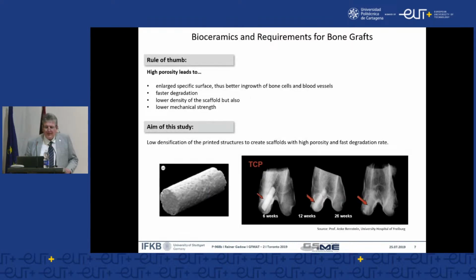So, bioceramics and the requirements for bone grafts. That was my talk until now. And we can say that the porosity we have learned, we have analyzed from extracted pieces of human bone, shows that, always under the condition that we can avoid any inflammation and infection. That means that we have perfect sterile conditions during the operation. And so we have a distinctly enlarged specific surface, as not only the outer surface, the total accessible surface is involved, and we have a very good ingrowth of the bone cells.